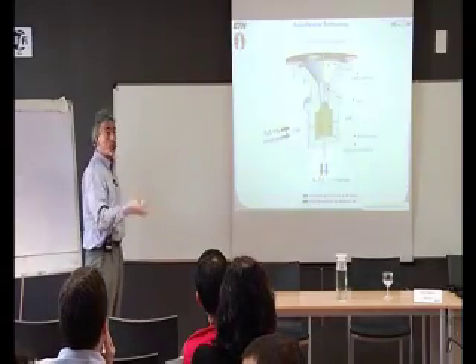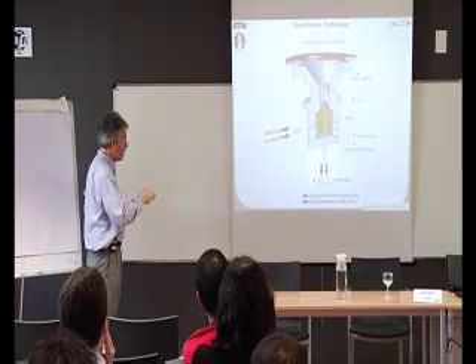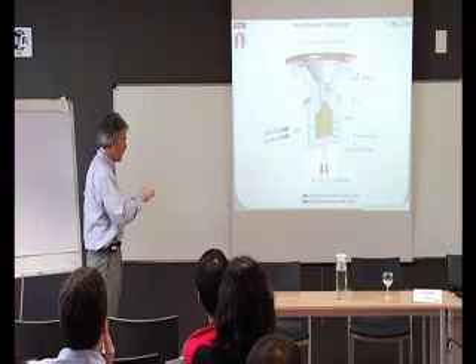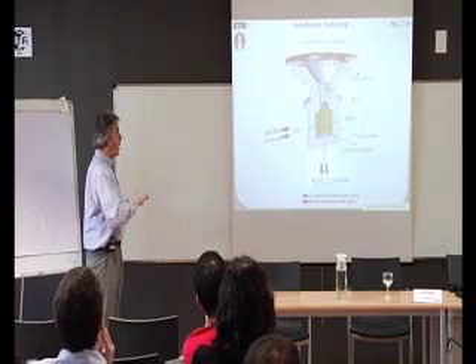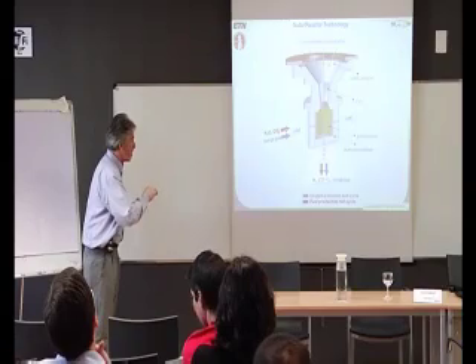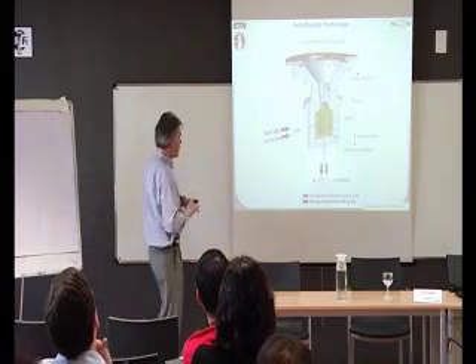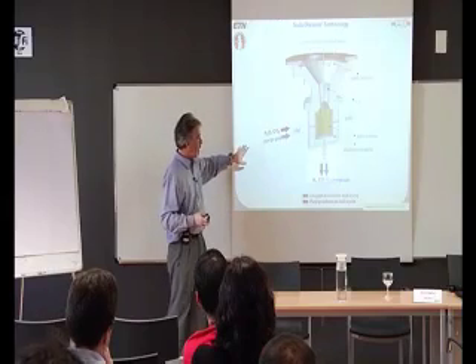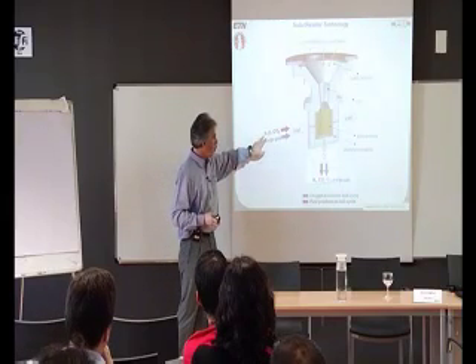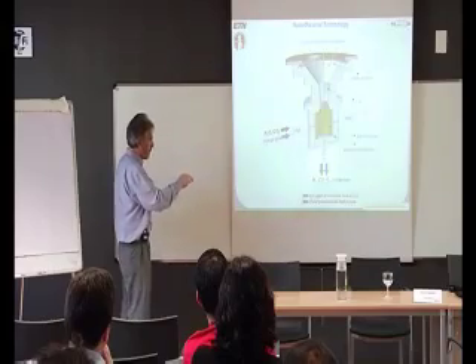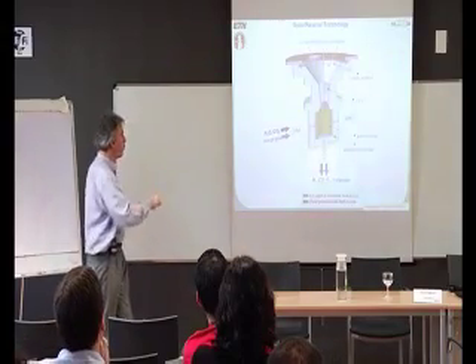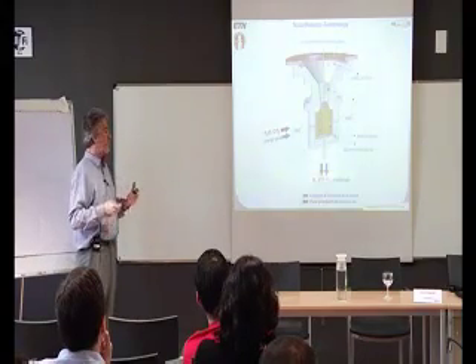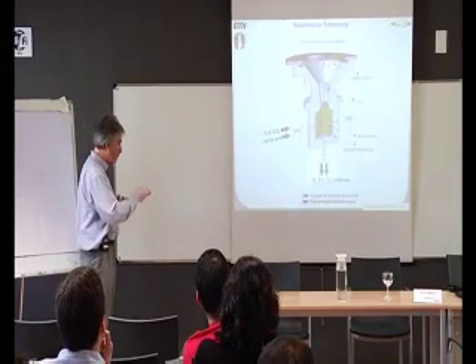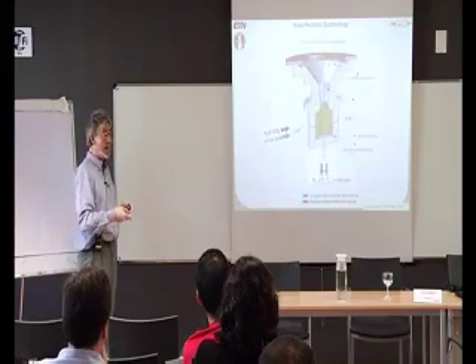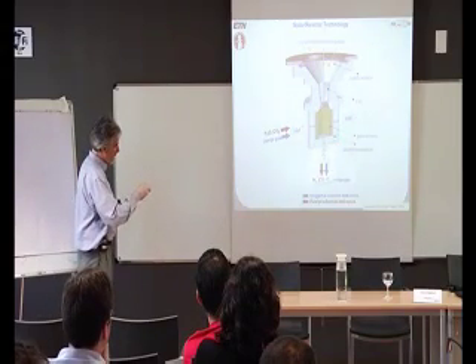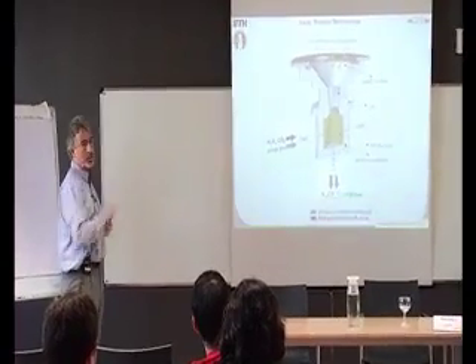This is one way we want to proceed. The other thing is the material that we are using basically is not optimized for the flows that we are using. We are putting too much excess. We are feeding too much water and CO2. We will have to match the flows to the material that we have, and it depends on the kinetics, and on the rate of heat transfer. So basically two things. Improve the reactor so that the heat losses are reduced, and match the ceria to the flows of the reacting gas and to the rate of heat transfer.